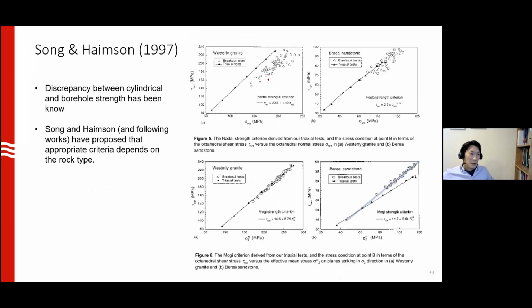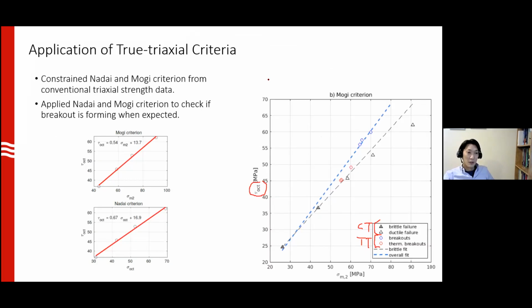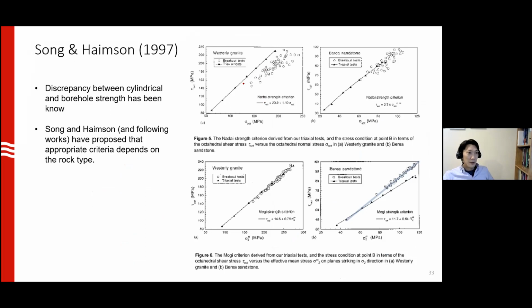Actually, this is somewhat known from past studies. This is a study from Song and Haimson, 1997, which does a very similar comparison to what we did here in this previous plot. They found that agreement between a triaxial test and a breakout test depends on the rock type. So left column is Westerly granite, right column is Berea sandstone. They understand that the Nadai criterion works better for high porosity rocks, whereas the Mogi criterion works better for Westerly granite.